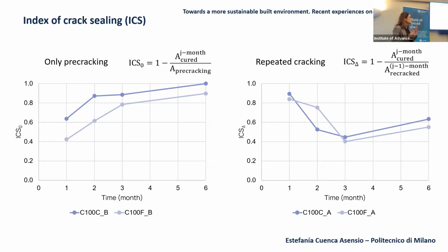So, in order to assess all those things, it's important also to quantify the effects, not only in a qualitative way. So here in this graph, we have focused on those mixes, and we have calculated several indexes called the index of crack sealing in order to evaluate only the surface of the crack. As you can see here, we have a ratio, a relationship between the area of the crack just after the cracking, and the area after several periods of healing, curing.